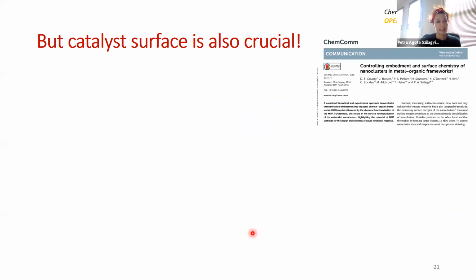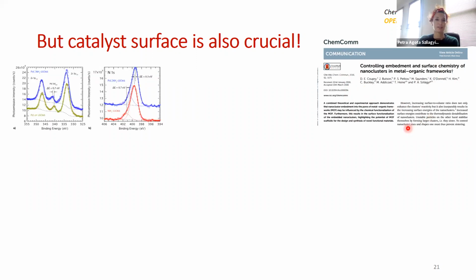So far we've looked at really the catalyst and its atomistic structure and the chemistry, so the size effect as such on these particles. But particularly for heterogeneous catalytic reactions, it's not just the particle size that's of importance, or if you wish, the proportion of surface atoms, but also the chemistry or the chemical state of the surface atoms. So in order to look into this in more detail, we stuck with the previous system. So you can see that this is still palladium in amino UiO-66.